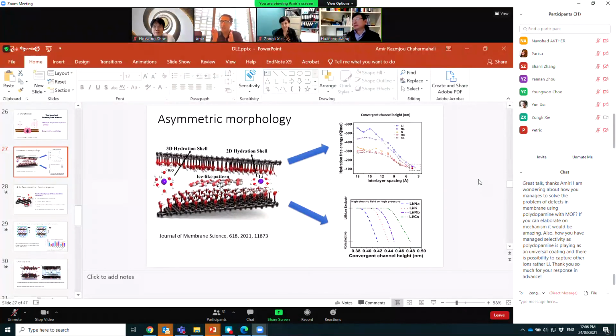Yeah, okay. I couldn't give a clear number, because there are many parameters: ionic strengths, concentration, the lengths, how you put the electrodes, and even the electrode structure and shape contribute to that. The distance of the electrodes, all of those parameters contribute. But purely about this one, what we found is that as the ion moves along the length of the nanochannel, the shell changes. Yeah. All right, thank you.